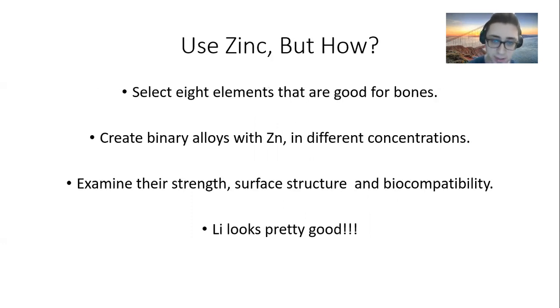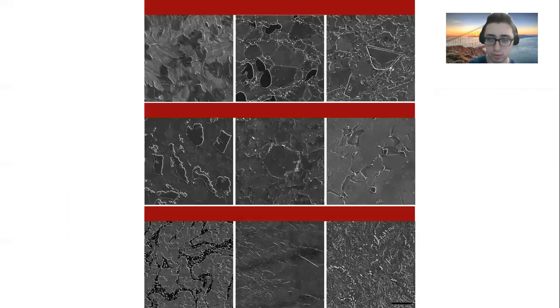So we're gonna use zinc, but how? What the researchers did was they selected 8 elements. These elements are already good for bones in general. They created binary alloys with zinc in different concentrations, like 0.1%, 0.4%, 0.8%. They examined these alloys' strength, surface structure, and biocompatibility. And it turns out these zinc and lithium alloys are pretty good actually. I'm gonna show you the pictures in a second.